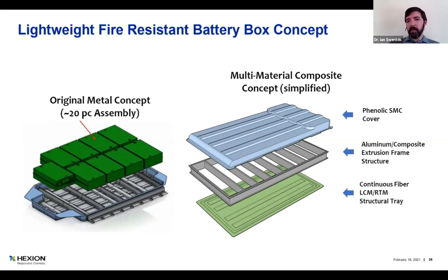Yeah, absolutely. And while not an automotive application, we have some interest, I'd say strong interest, even from aerospace, where there is a greater use of solid state batteries in portions of aerospace, without going into detail there. There are multiple strategies to deal with that, but one of them is to isolate the batteries themselves into smaller units so that there's no monolithic battery pack, but several smaller discrete battery packs. And there, where you maybe don't have as big an issue of cascade failure, you still have the issue of high temperature failure. And so a phenolic cover enclosure is readily realizable. It's certainly a key target for some of those areas. Phenolic resins are already a longstanding approved material for aerospace. It's relatively new to automotive applications.